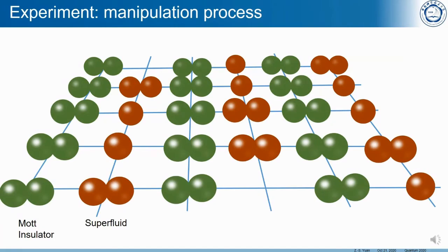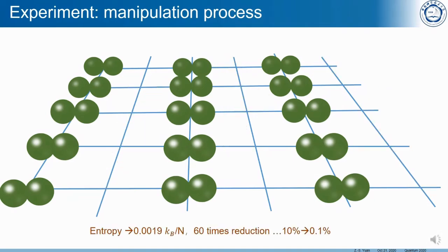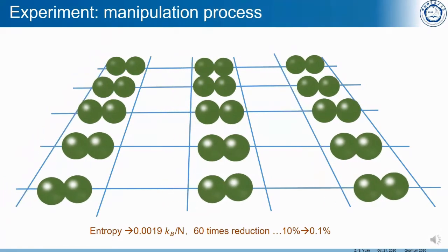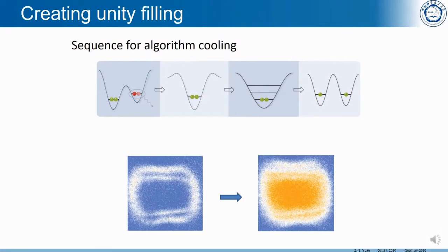This cartoon illustration shows that after the cooling, we have the Mott insulator with low entropy, while the superfluid has higher entropy. We then flip the spin of the atoms in the superfluid, and use an on-resonance laser beam to blow them away. Therefore, we leave only the Mott insulator with very low entropy, and we use an adiabatic passage process to transfer the 2-0 configuration to the 1-1 configuration, and finally we achieve a unit filling lattice.